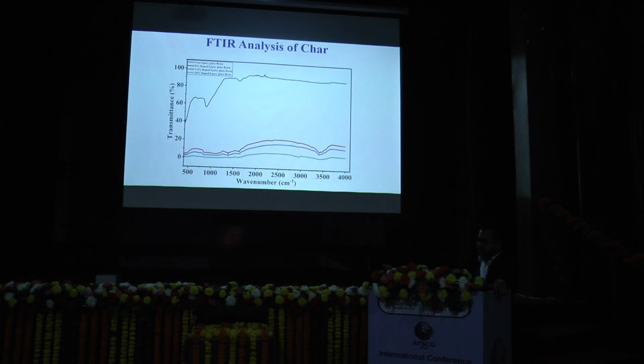This is the FTIR analysis. The FTIR spectrum represents the chemical structure of the residual char after burning. In the doped composite, we can observe peaks in the 1000 to 1200 region corresponding to P=O and Si-O-Si formation. These confirm the formation of a phosphosilicate reinforced protective char layer. We also see a reduction in the CH peaks in the doped sample, and in the graph we can see that the 10% doped composite gives good, high char formation.